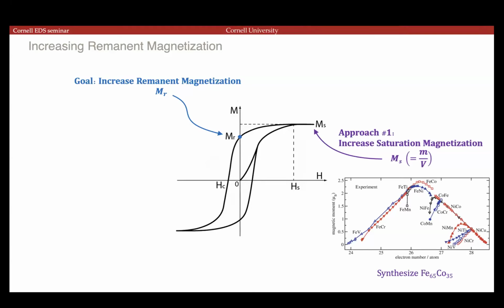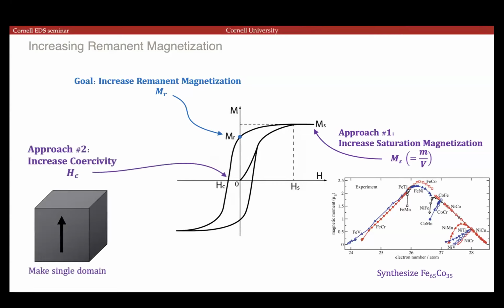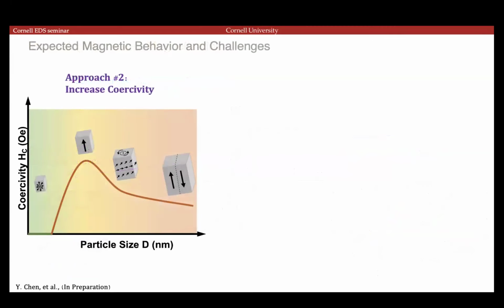That's one way. And then we also can try to stretch this curve wider to get a higher coercivity and therefore lift this point up just by stretching the curve. So the way to increase the coercivity is by making the material single domain. In other words, there's just one net magnetization within the material and no other sections with opposite magnetization. If you compare coercivity as a function of particle size, though, this becomes quite a challenging thing to do.